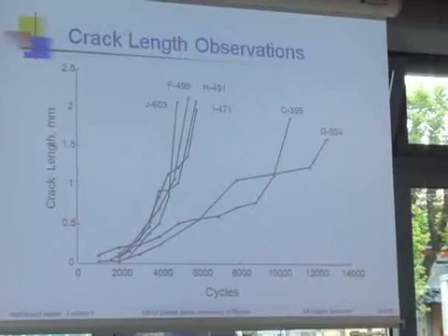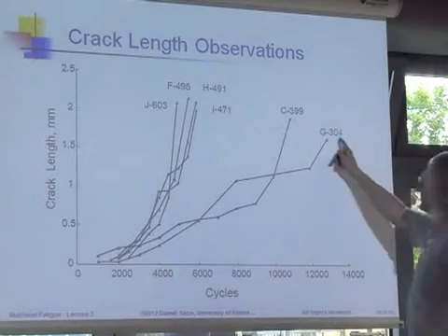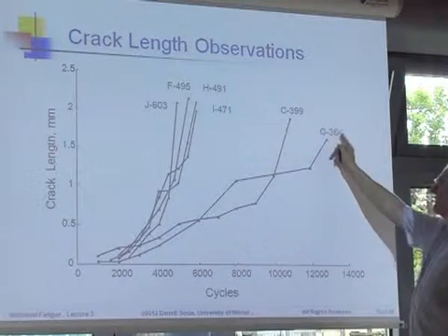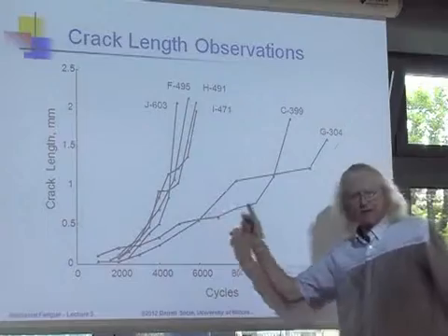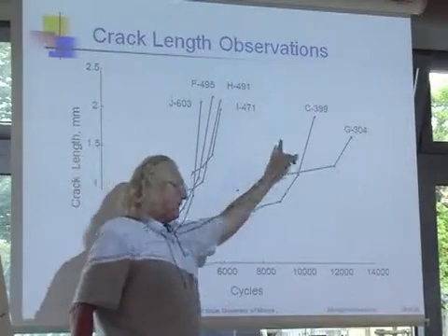By the way, this one I showed you yesterday, now I can tell you that these actually are the stresses that act across the shear plane. Shear stress is the same for every one of these, and you can see when the normal stress is not very high, the life is a long time. The reason is because it inhibits the growth of the microcracks.